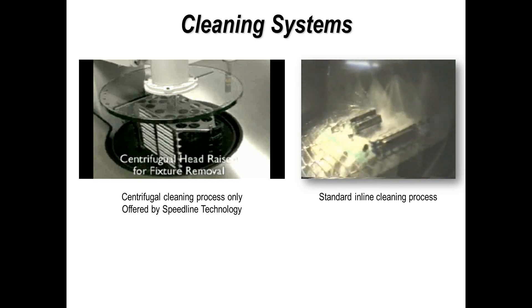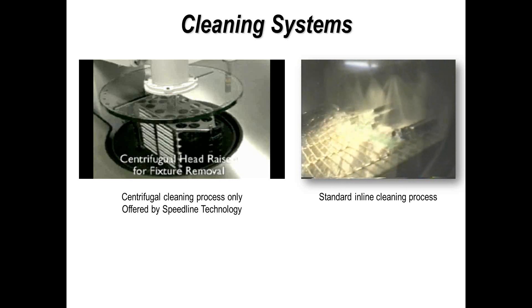One thing to bear in mind is that the mechanical force applied with a spray system can affect very small boards — it can lift them up and possibly damage them. Large boards are generally not a problem. In a centrifugal system, if you've got a board with very heavy components like ceramic chip carriers or ceramic column grid arrays, that centrifugal force may deform some of the leads on the components. So consider that when evaluating these types of processes.